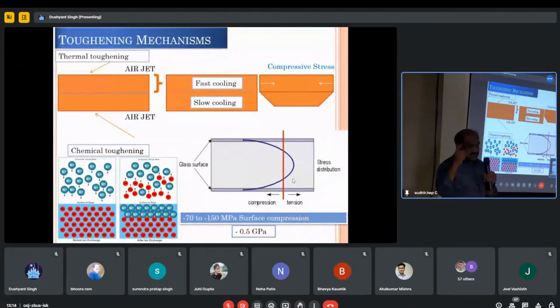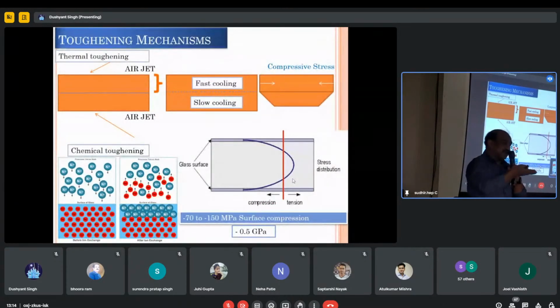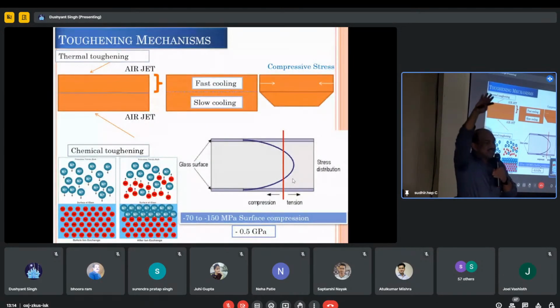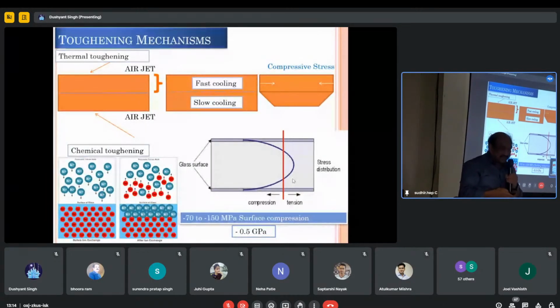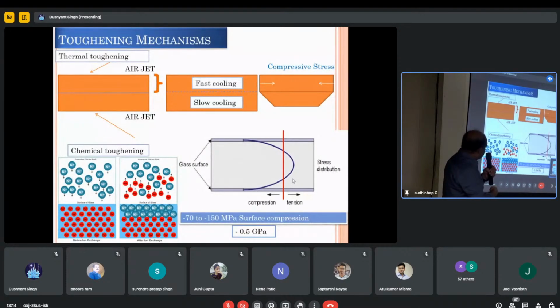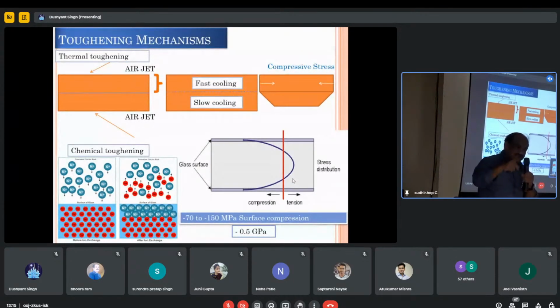In the beginning I was telling that if you cool the same glass at different cooling rates, you will end up with different densities. If you cool it faster, you will have a lower density. If you cool it slower, you will have a higher density. In thermal tempering, the glass block is exposed to a high temperature and suddenly quenched. As glass is a thermally insulating material, the surface cools very fast compared to the interior. So there will be a different density in the interior and the surface. Because of the density difference, it pulls the surface and creates compression, and that strengthens the glass. That we call thermal tempering.